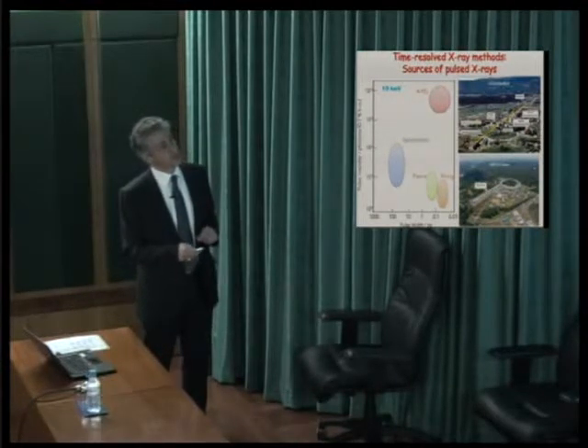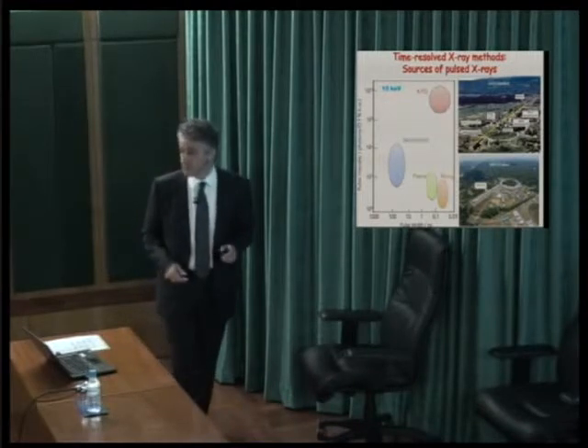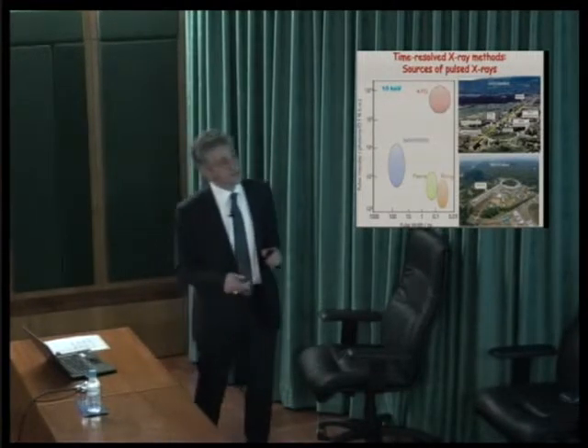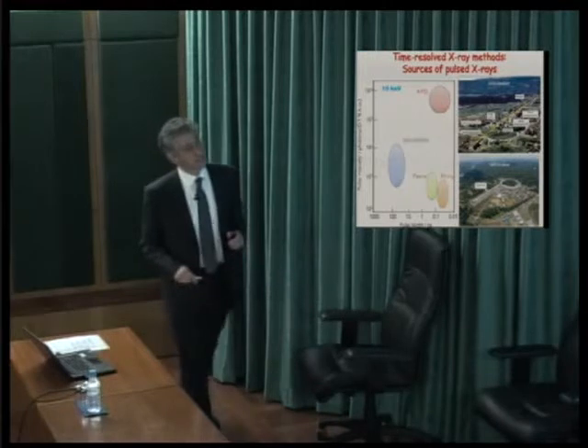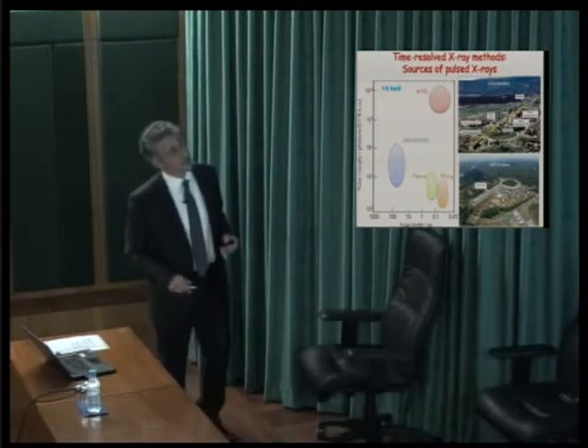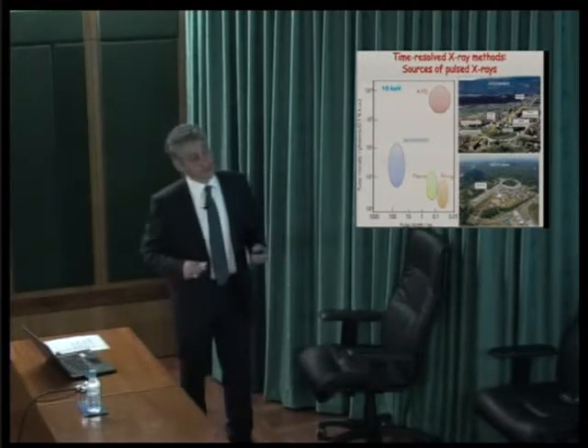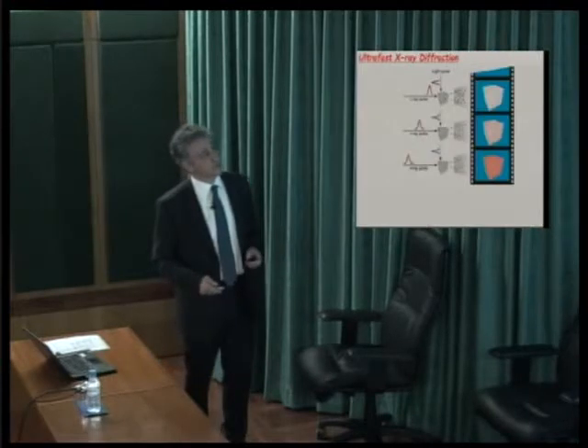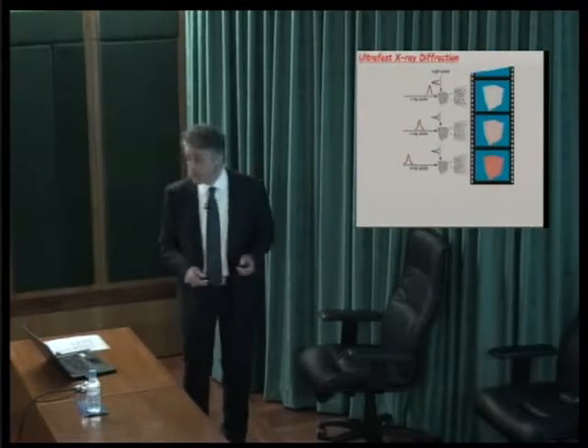And look at the jump that you get with a free electron laser. For the same widths of about 50 to 100 femtoseconds, you have 11 orders of magnitude to 10 orders of magnitude jump in flux. So you understand why this is such a game changer. Now, what can you do with these machines, or what can you do in general with pulsed X-rays? You can do ultra-fast X-ray diffraction.